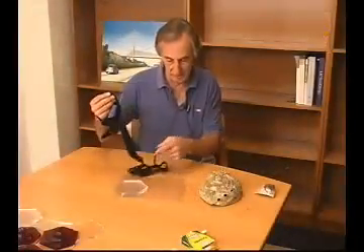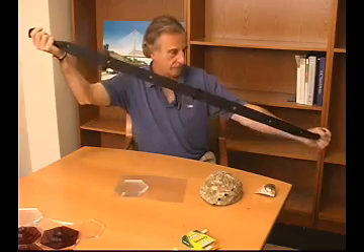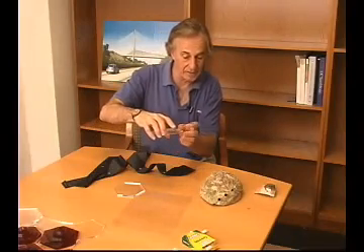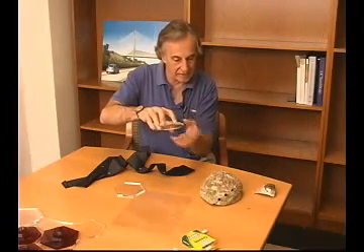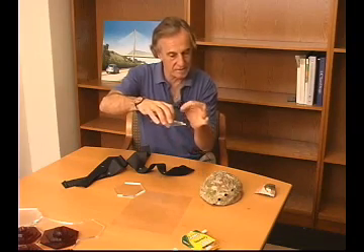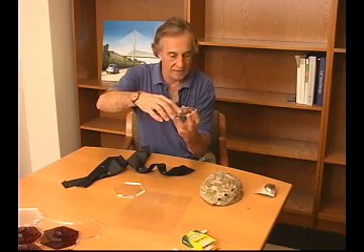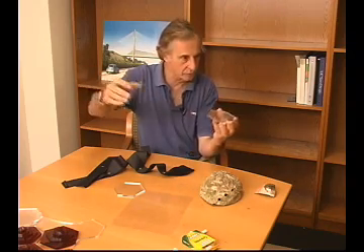Imagine that these are some of the polymer molecules comprising these proteins. When I pull this, rather than breaking, it gives gradually — and then it breaks. So one tile is attached to the other by strings like this, like little springs. When the tiles slide, all these polymer molecules are stretching and stretching. It's only in an extreme situation that it would break apart.